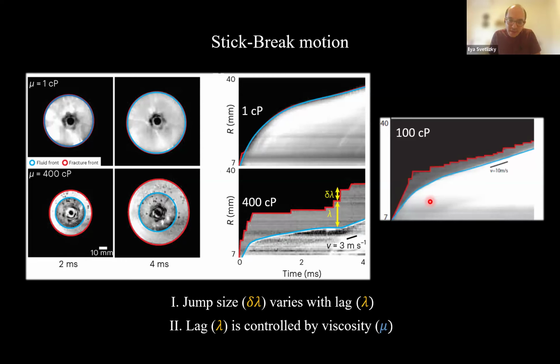volumes. Maybe I didn't say, it's a syringe pump. It means that we actually control the displacement of the pump. We don't keep the pressure of the pump constant. This is almost impossible to do at milliseconds, right? So it's a high pressure syringe, where you control the end part of the syringe. So basically the injected volume, and then the fluid just decompresses.